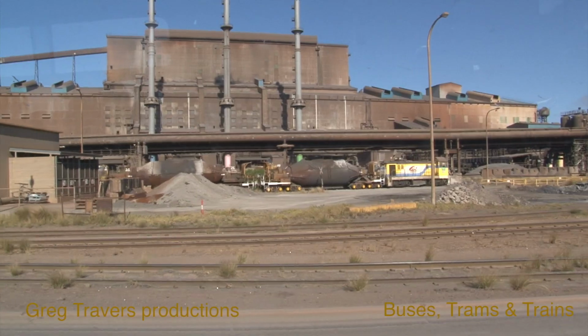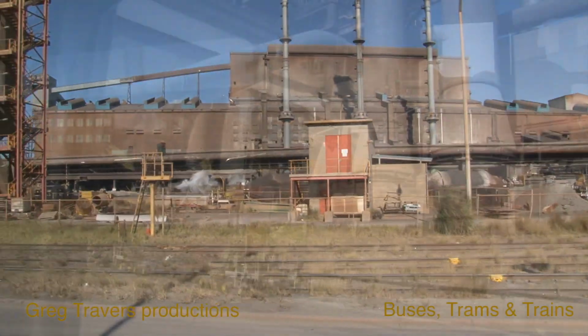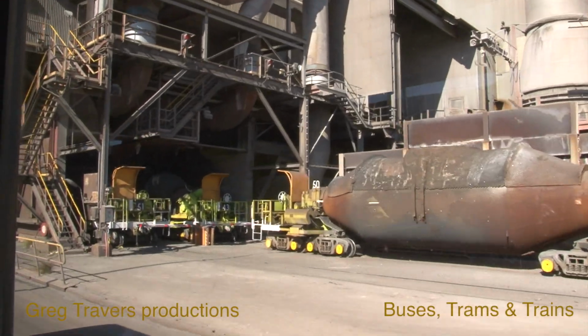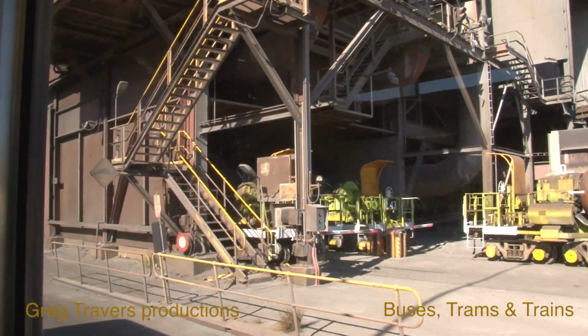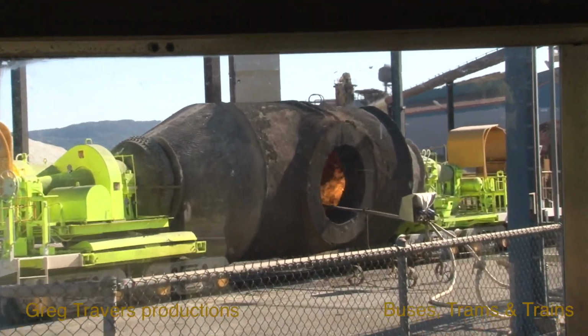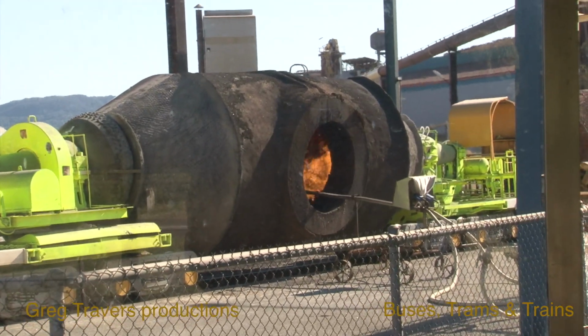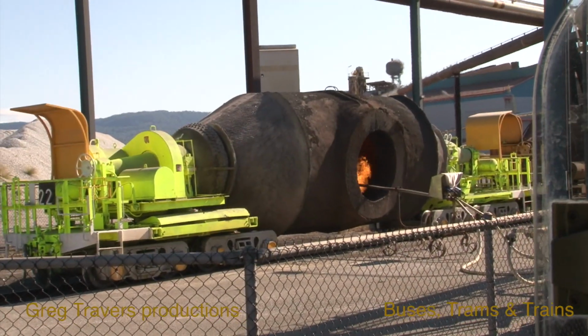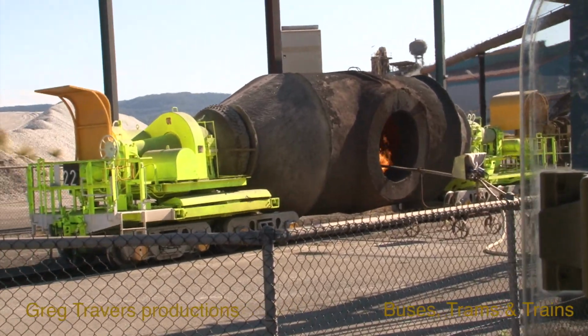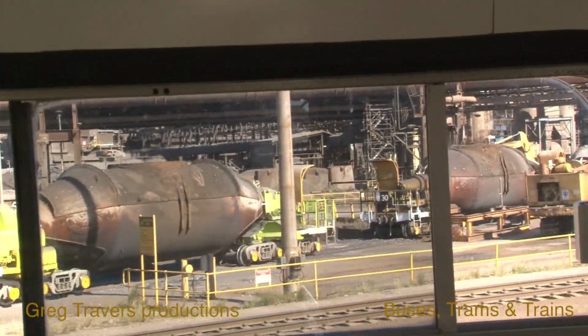So those vessels will be transporting the iron from the blast furnace around to the steel making unit, draining that iron that's forming at the bottom. It'll be about 1600 degrees centigrade, draining it into those torpedo ladles. Anything that we're transporting liquid iron or liquid steel in will be a steel shell, and then they'll have a refractory lining on the inside. And that refractory lining has got to be heated up to about 900 degrees centigrade before we can introduce molten material into it, because otherwise we're going to get thermal spalling and some unhappy steelworkers here that have got to pay for more bricks.